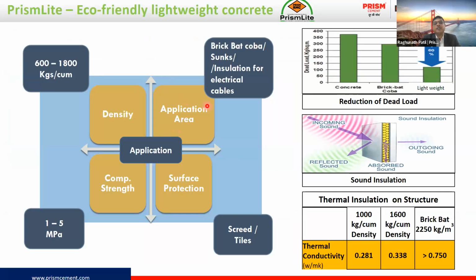This lightweight concrete is used as a replacement for the Brick Bat coba. Generally Brick Bat coba is used on the terrace slab to cover the waterproofing layer. So in that Brick Bat coba replacement, this is the best solution. Also for filling purposes, for insulation, or for filling sunken portions, this concrete is very useful. The compressive strength is 1 to 5 MPa. That's why we suggest it only for non-structural applications.